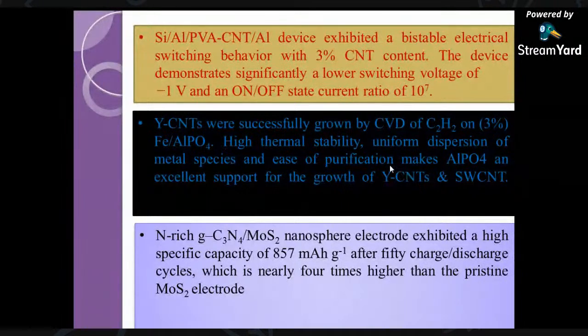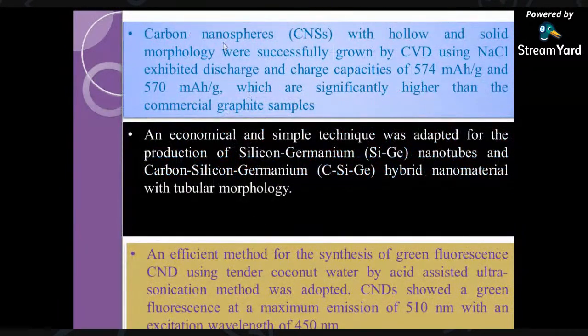Then we have a catalyst called iron loaded aluminum phosphate, which is a good candidate for creating Y-shaped carbon nanotubes and single wall carbon nanotubes. Then the heterostructure of carbon nanotubes, carbon nitride and MoS2 is a good candidate for battery application, which gives a specific capacity of 857 milliamp hours per gram after undergoing 50 charge discharge cycles. And then we have nanospheres, a good candidate for lithium-ion batteries, which give a higher charge capacity, greater than the graphite.